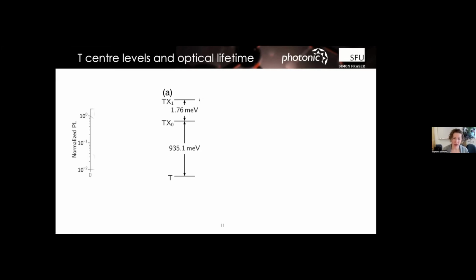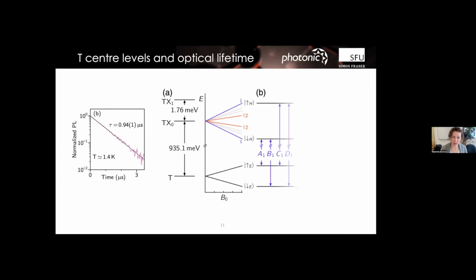Nice and easy. The lifetime of this thing is in a Goldilocks regime. So it's around a microsecond, which means if you ever want to put this thing into a cavity and Purcell it, which you would want to get rid of the sideband anyway, you can then push it down to the couple nanosecond regime and not have to worry about picoseconds. But it's not too long-lived that it's too dim to see, right? You have to start with something. So for us, it's a little bit on the long side for the Goldilocks regime, but we're really happy with this time.